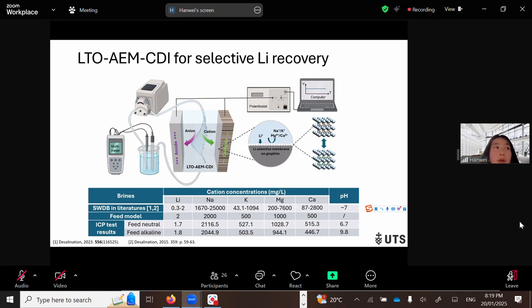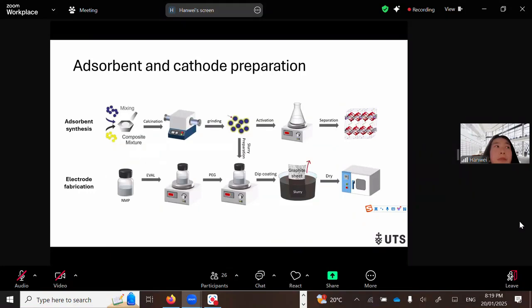Different from the previous two strategies, in this one we directly use the simulated seawater brine to test the MCDI performance based on the literature data. And we test both under neutral and alkaline conditions. This is how we synthesize and fabricate the LTO powder and LTO electrode. We use a calcination method to generate lithium adsorbent, and using a dip coating method to fabricate the cathode directly on the graphite sheet.